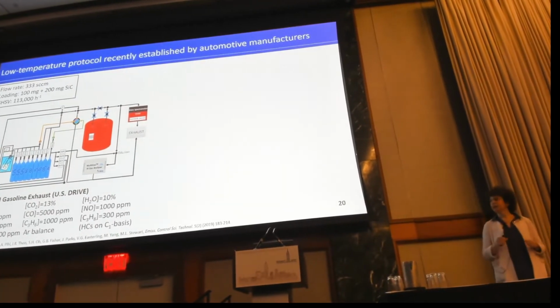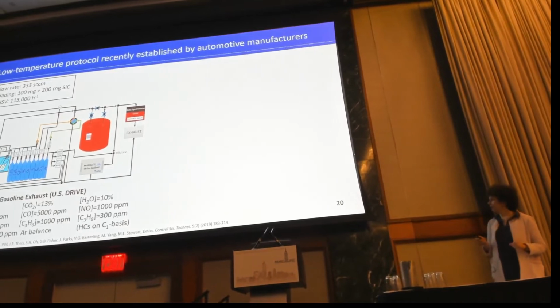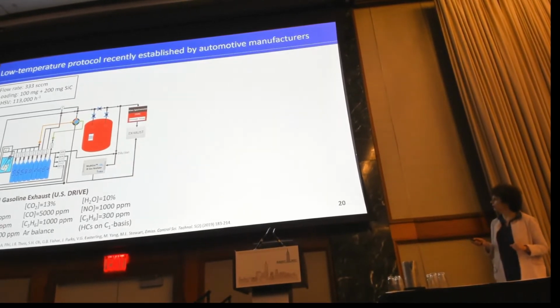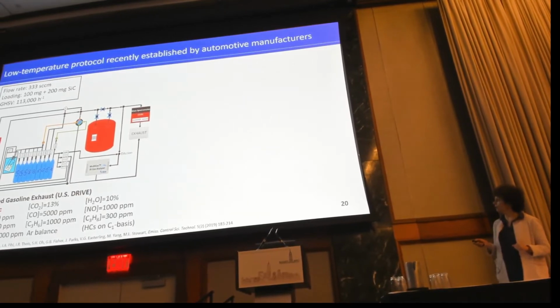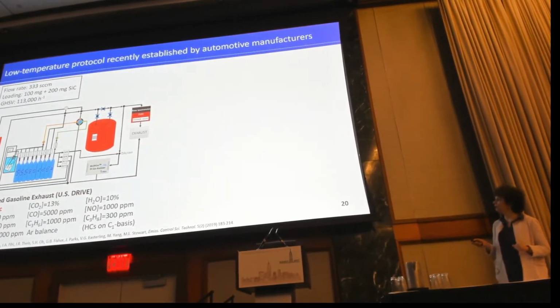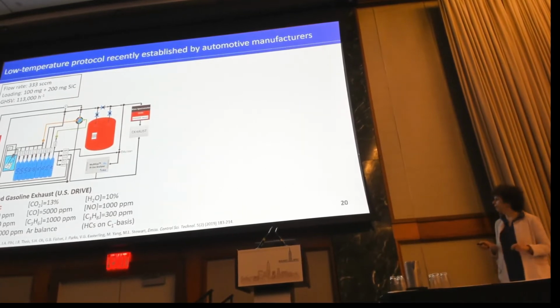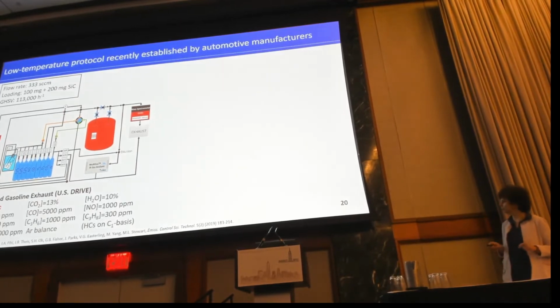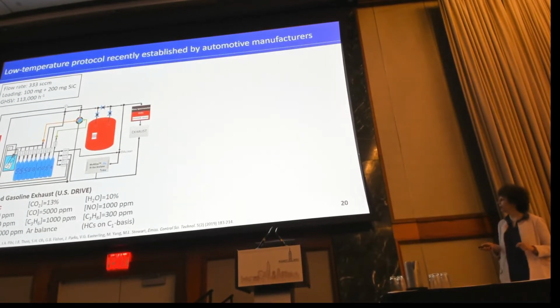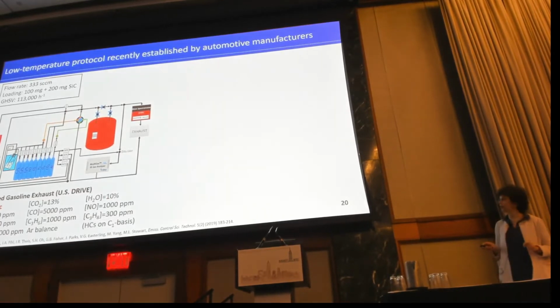Okay, so you have seen this cartoon before, but the conditions are different. The flow rate is 333 sccm. We load 100 milligrams of catalyst that in this case we dilute with 200 milligrams of silicon carbide. The conditions that we're using are shown here. We want to use a simulated gas exhaust stream, so the amount of oxygen is stoichiometric. We have 10% water, hydrogen, CO, NO, and a series of hydrocarbons. In this case, we have iso-octane as a liquid hydrocarbon that is introduced in the reactor with a bubbler that is immersed in the water bath that is set at 0 degrees C.